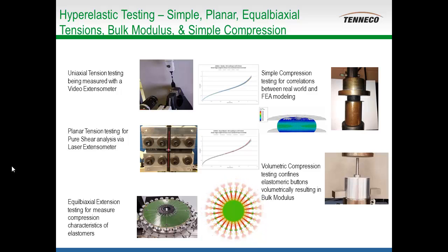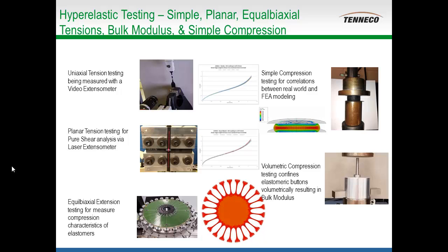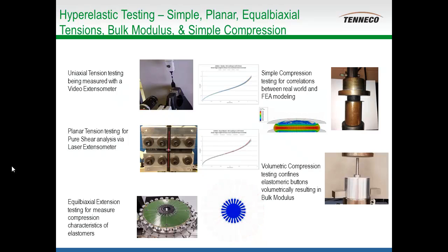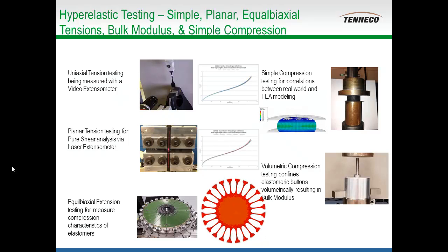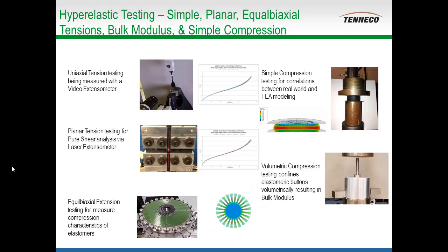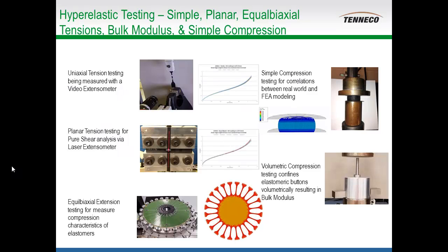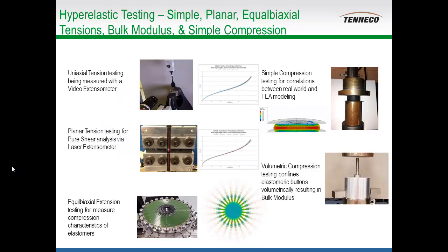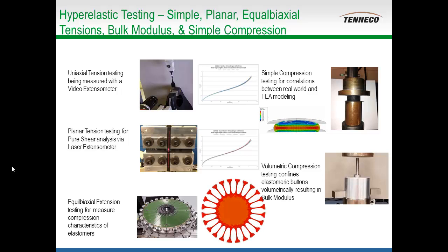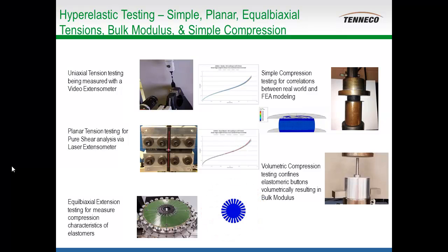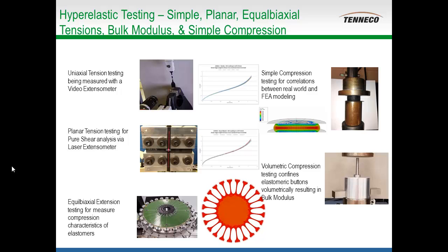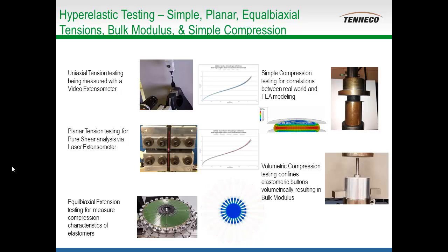Although it's not part of the hyperelastic modeling, because of the other material testing that we're doing at this time, we always do a simple compression test. We have some automated batch processing where we use that simple force displacement curve. Although it's a simple compression button, the states of strain are mixed. So that gives us a very simple part to do some automated correlation that our material properties are predicting the force displacement curves correctly.